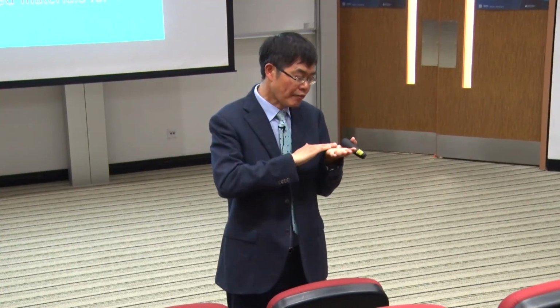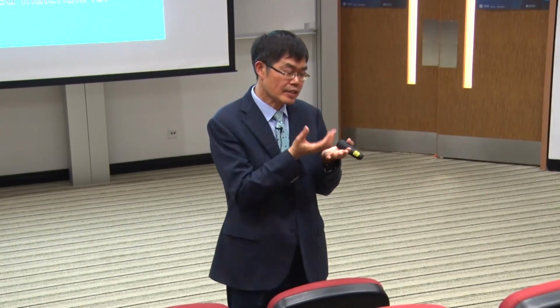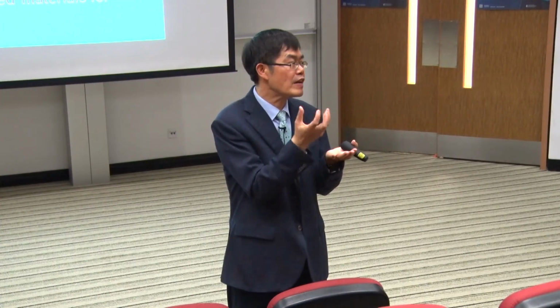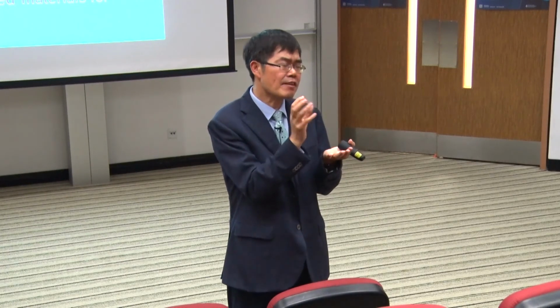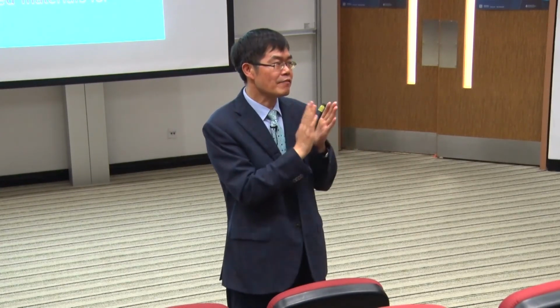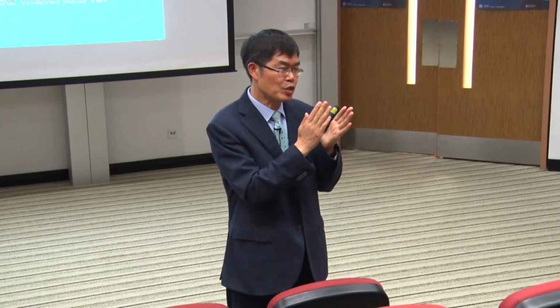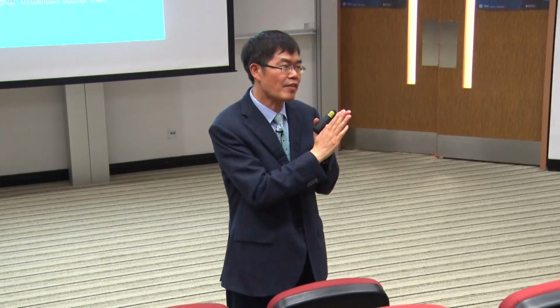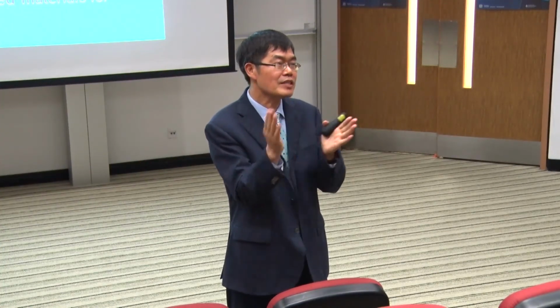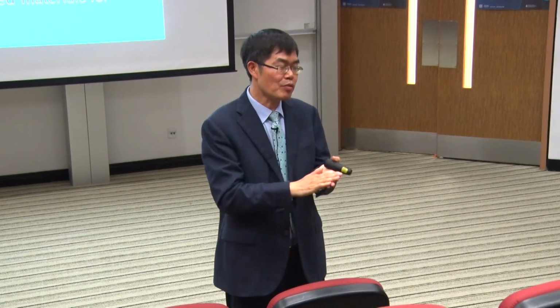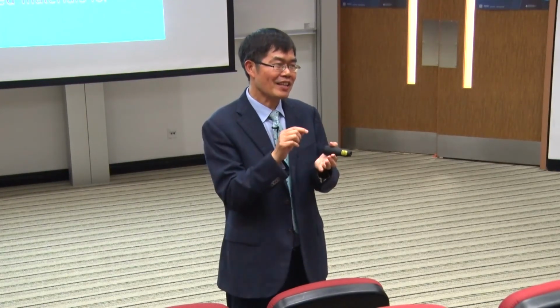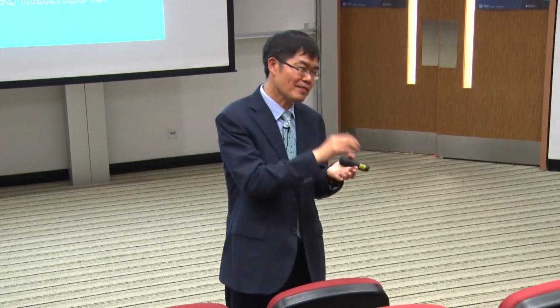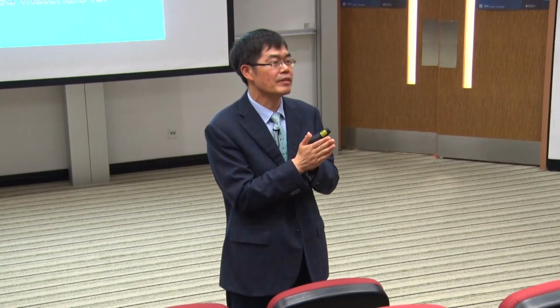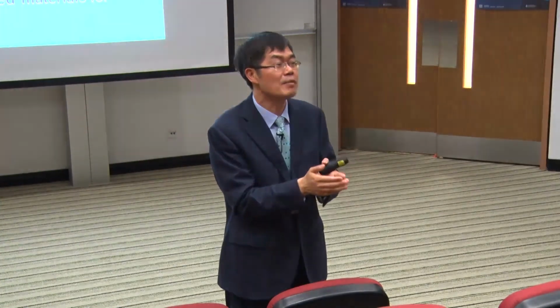And also, after this coating, basically this layer is not smooth. It has a very rough surface, and it's a kind of porous structure. So we found that there is very good adhesion between this coated current collector and the active material. Adhesion is improved, that means the electrical conductivity is improved. Second, it's not so easy to detach during charge and discharge between the current collector and the active material. So that also can improve the cyclability.